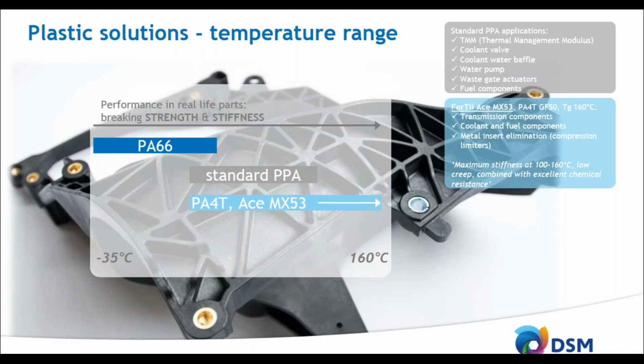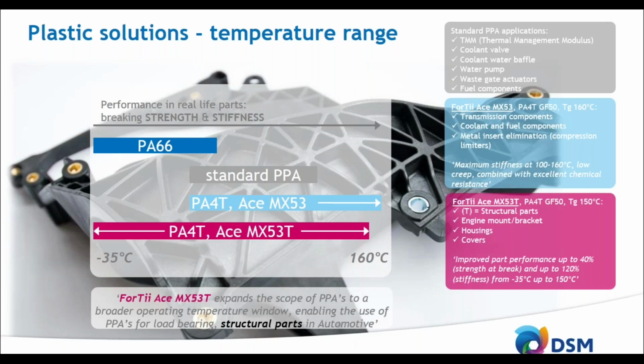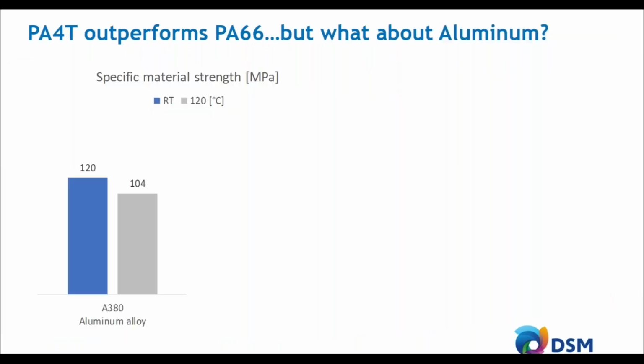But is this also enough for structural parts? If you look, for example, at an engine mount or a housing, they also have to work from minus 35 or minus 40 degrees C up to around 150 degrees C. It has to work over the entire temperature range. And with this latest innovation, with this latest material, ACE MX53T, we are able to expand the scope of PPAs really into load-bearing structural parts for the automotive industry. And that's unique in its kind, and that's something that we will dive a little bit deeper in.